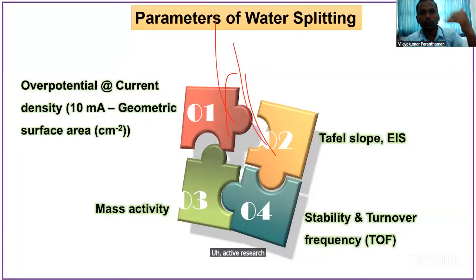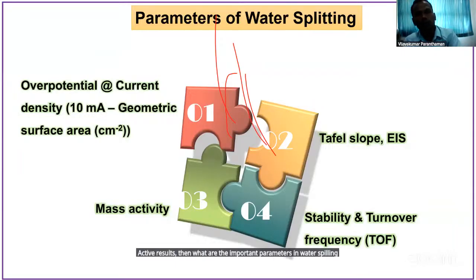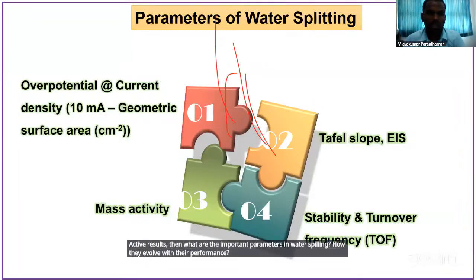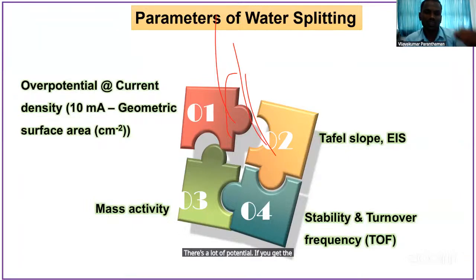Then what are the important parameters in water splitting? How do they evaluate your performance? This is the overpotential. If you get a very small overpotential, your material is a very good catalyst. Before the calculation of the overpotential, we need to know the geometric surface area. The geometric surface area is different from the electroactive surface area. The geometric surface area is how much area you coated with your material. Like if you use nickel foam, how much area of nickel foam is immersed in the electrolyte solution. That is the geometric area.